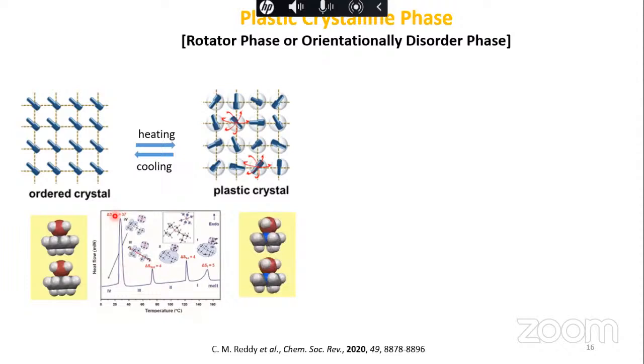This peak is very high because you are taking a lot of energy, and the melting peak in such cases is normally smaller than the order to disorder phase transformation. Why? Because if the crystal directly goes into the melt, it attains all rotational degrees of freedom plus translational degrees of freedom. But if you are going through this phase, you already have a lot of energy in the system, because your system has very high entropy, since you already have these rotational degrees of freedom. That means you have already put a lot of energy into the system. And when it melts, all you gain is only the translational degrees of freedom. That is why the energy required to go into the melt here is not as high as when you are directly transforming these crystals into the melt.